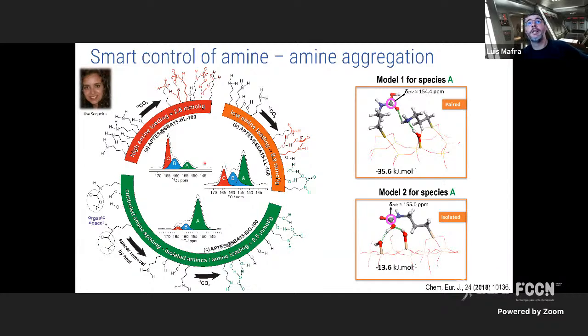done all this work. She has done grafting in a conventional way, putting as much amine as possible with a very high loading, 2.8 millimole per gram. Then we try to dilute more or less 3 times. And we see that the spectrum changes like that. You see that as you dilute the amine coverage, you start to favor the intensity of resonance A. With our approach, where you add a bulky spacer, you can now really reverse these intensities from here to here. Now A is the one that dominates completely.